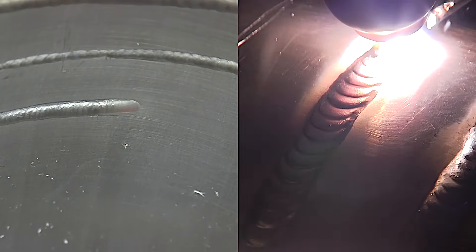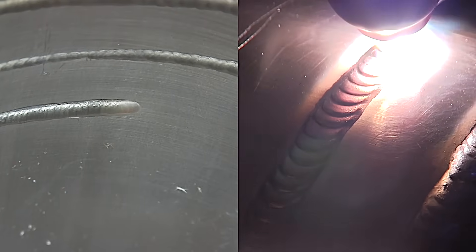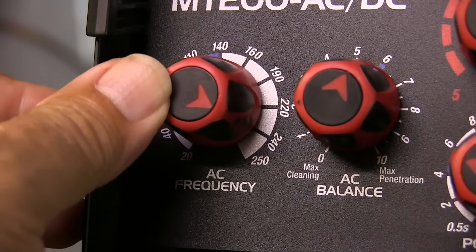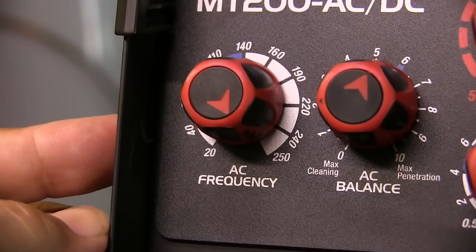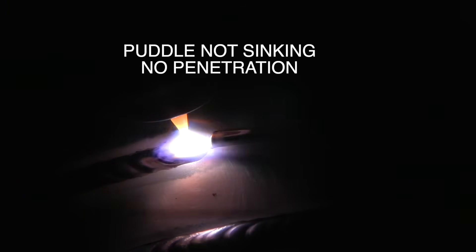But when I turned it up to 250 hertz, same amperage, same travel speed, same filler metal size, everything the same. I got a very different result. You see that bead is just laying up on top there.